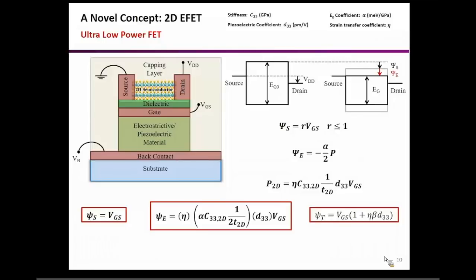But now when we apply this gate bias to this transistor, it is also actuating this piezoelectric material. The piezoelectric material is then expanding, and this expansion is creating a decrease in the band gap in the 2D material. And of course, you have to clamp it in a rigid structure so that whatever expansion happens to the PZT material gets maximally transferred into the 2D material. Okay, so there is some structural engineering that also needs to take place. But if you assume that I can efficiently transfer this actuation into this 2D material, then I will get an additional band movement because of a decrease in the band gap.